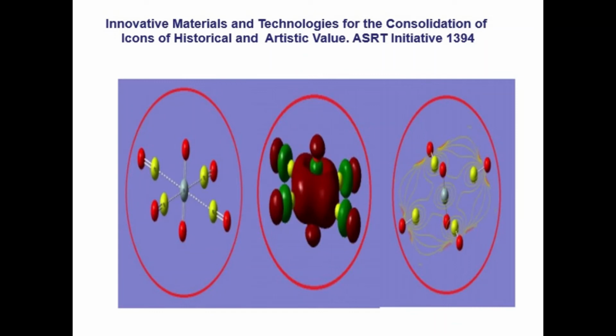And we chose to make a bimetallic method of preparation. As we can see, we have here two metal oxides, or a bimetallic, both in nanoscale. We produce them as a colloid, as indicated in the bottle, and as a powder. And then we make UV-visible analysis to be sure that this works to prevent the light. And then we make an analysis of the surface with the electron microscope to have a look at the structure of this bimetallic nanomaterial. And then we put it as a protective layer.